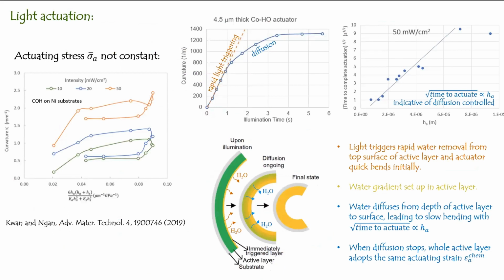What about light actuation? Now we do the same plot, plotting curvature versus that factor that we can vary by making different actuators. You don't see a linear plot anymore. So if you do the light actuation, the material is not giving you a constant average actuating stress, which is quite interesting, right? So the behavior is totally different. And if you look at the speed of the actuation, there is a fast range followed by a slow range. Okay, so this is actuation versus time. So initially the response is fast and then it slows down.